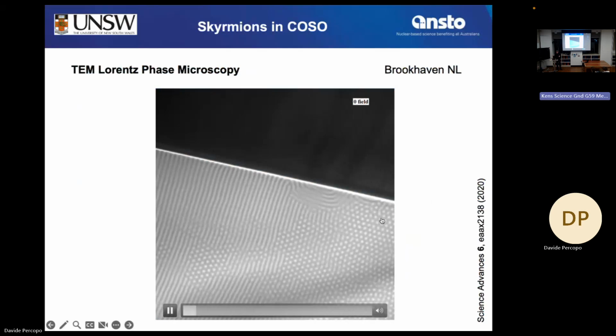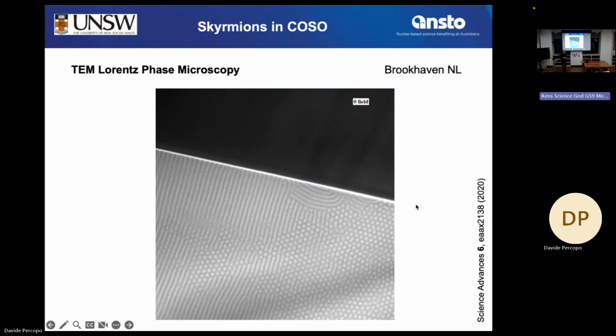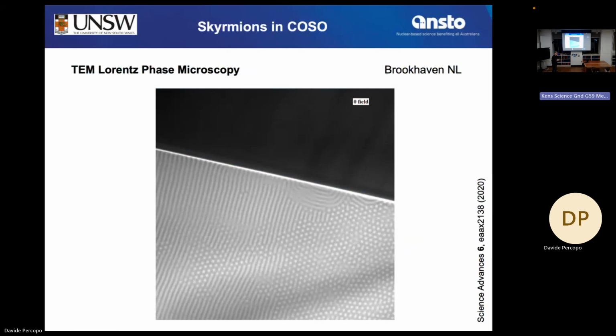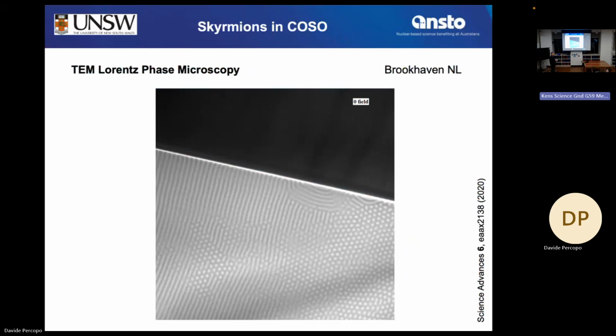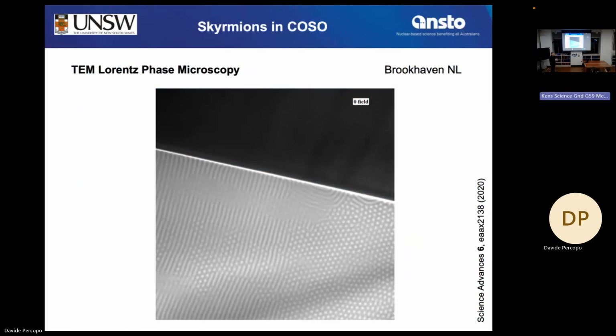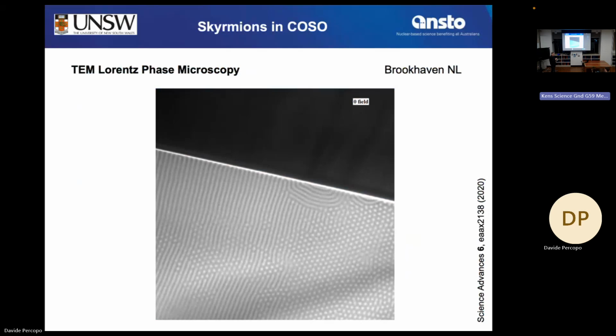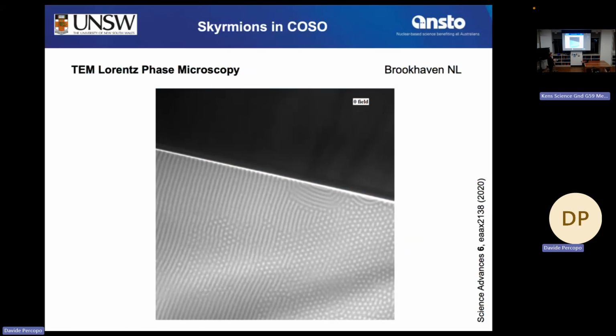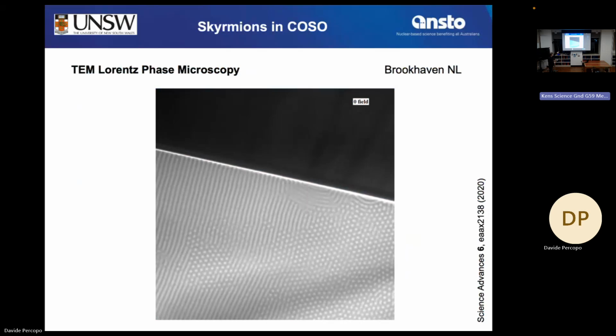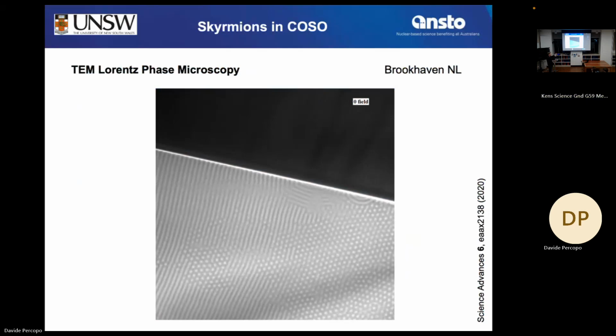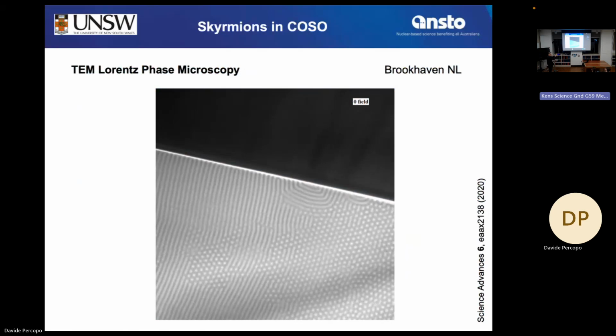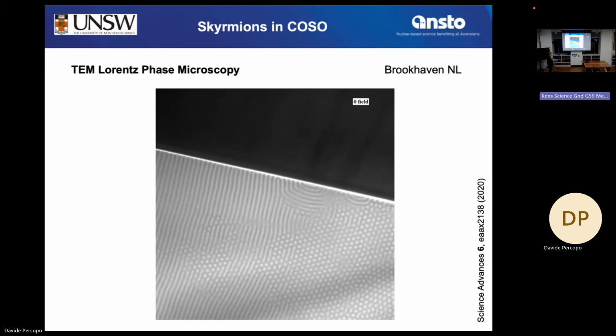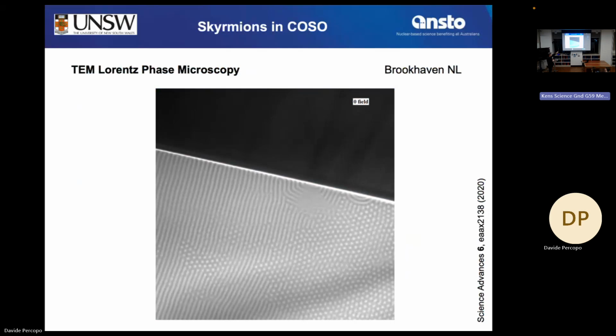I hope the video starts here. Yeah, it starts. So with the electron microscope in Brookhaven, we even took a real-time video that's shown here. The illumination time per point is half a second. It rattles a bit, but this is indeed real time. And I find that super amazing. If you watch carefully, they always change. They always wobble. They always move around. The hexagonal structure rotates. There is coexistence of helix and skyrmions, but sometimes skyrmions pop out of the helical phase.